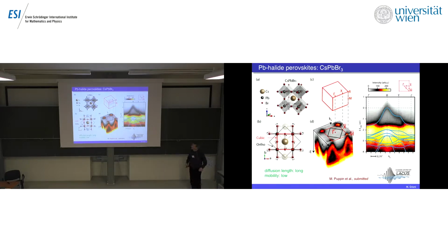But we don't see it to start with, and this is actually not unreasonable. What happens is that geometrically, the system is orthorhombic, so you would expect from Kittel to fold all the bands through the zone boundaries. But actually what matters is the spectral weight, and the spectral weight does not go with geometry, it goes with the strength of the potential. So clearly this is an indication that the potential associated to this superstructure is not so strong, and therefore there is nothing here. So this is a comparison of the result in high symmetry directions of the Brillouin zone with a DFT calculation.